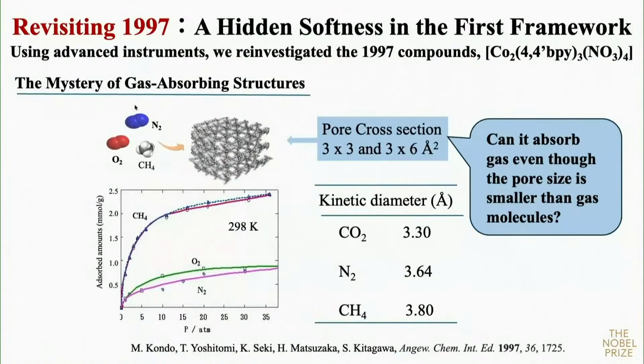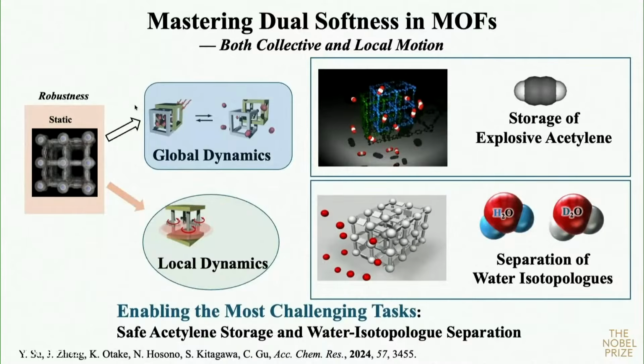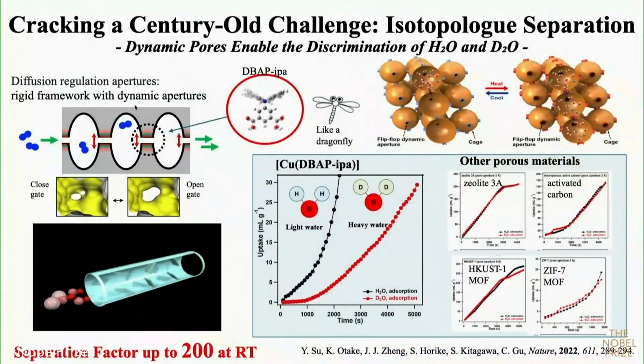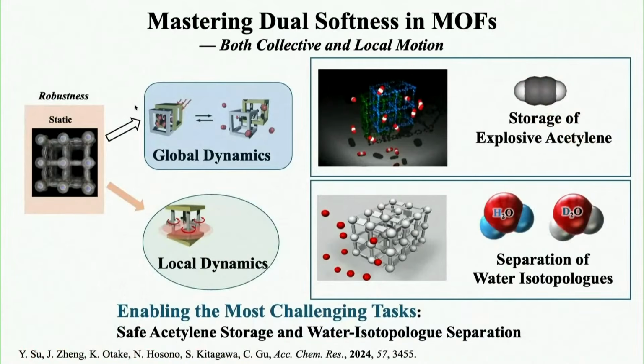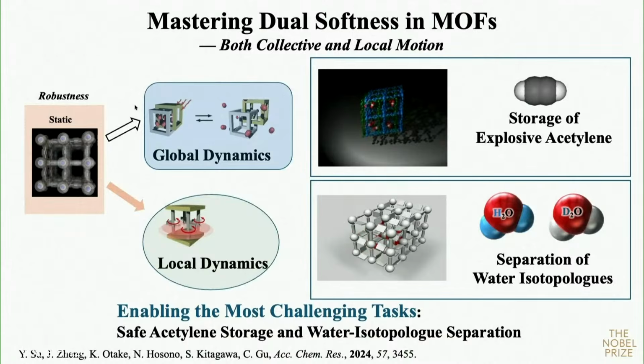So these are the results, and H2O diffuses much faster than heavy water in our system. But usual zeolites, activated carbon, HKUST1 MOF, ZIF7 MOF, and other MOF materials show exactly the same diffusion. So we succeeded in this kind of discrimination of these materials, with a separation factor up to 200 at room temperature. So this kind of flexibility, the dynamics, is very important for very difficult tasks.